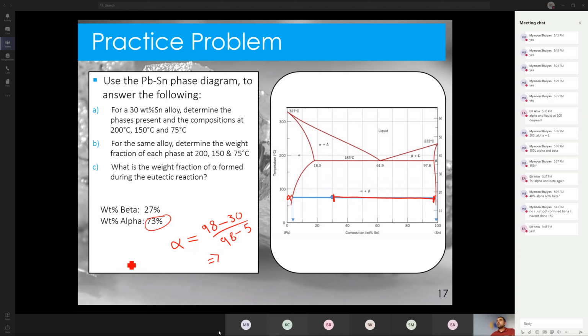And if it's 73% alpha, what's the rest? The rest is beta. Oh yeah, 71 is perfect, Maymoon. Yeah, 71% alpha is right on. It's just difficult to read the exact values on the screen. That's pretty good. Are we happy with this? So we got the idea of the amounts of the phases and what phases are present. Just for the sake of completeness, in this example we concluded there is 73% alpha and 27% beta. Suppose I was curious, what is the composition of the alpha? What is the alpha made of?